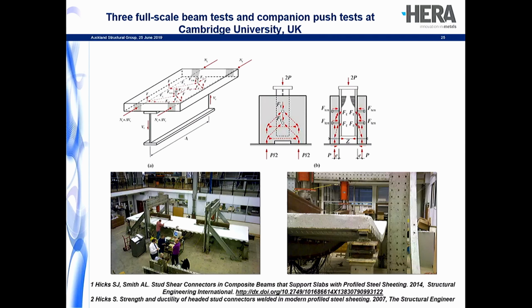And one of the other things to note from these full-scale beam tests is that, unlike anything that's been done internationally before, you might just about see it in this picture on the right, we actually instrumented every single cross-section all the way down the beam to monitor the build-up of the force into the steel section, and we also monitored the slip at every single shear connector position. So an extremely expensive exercise, but we did that just to find what the behaviour really was in a full-scale beam.